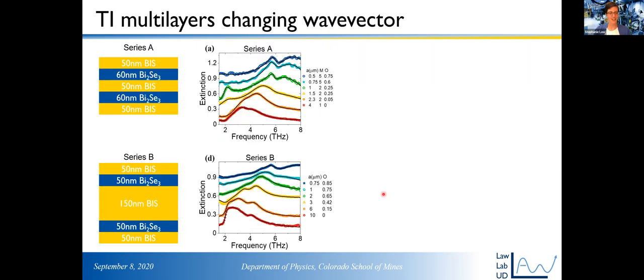So again, I think I put too much in here, but I was too excited. Basically, what we wanted to do is see, can we couple these states together? And so I'll just skip to the punchline, which is, yes, we actually can. And it's pretty cool. So if we change the size of this spacer layer, this was the first thing we did. We did two different series where we changed the size of the spacer layer.